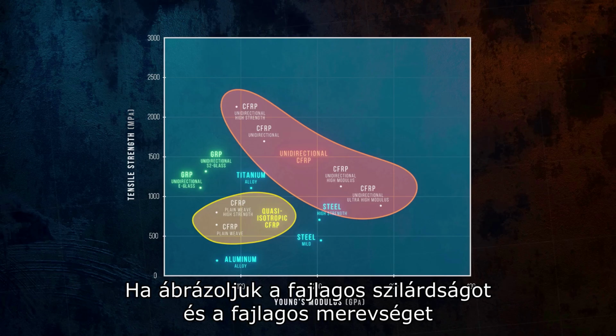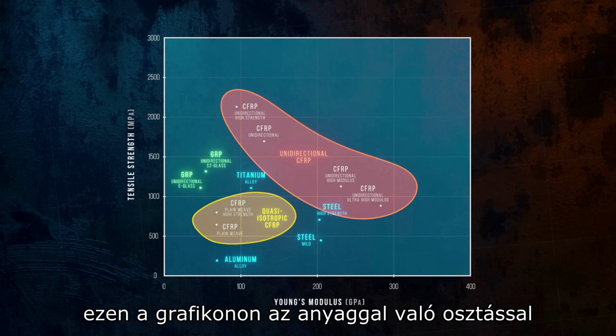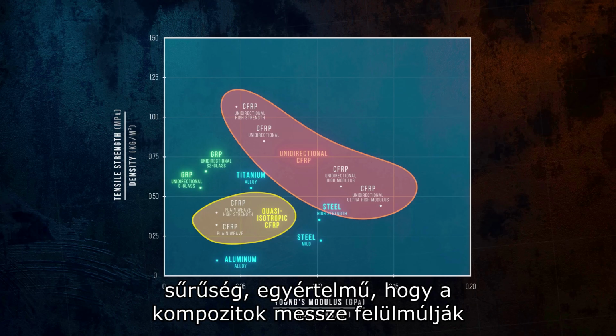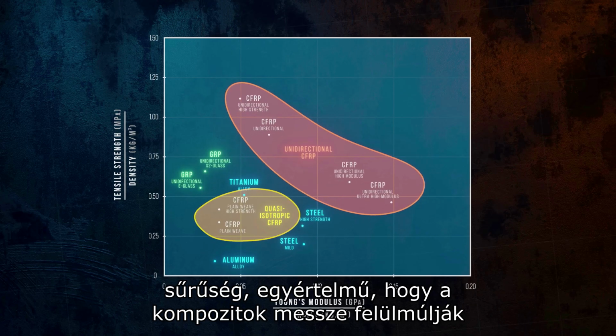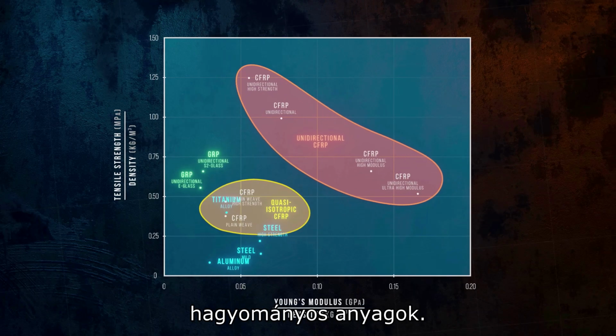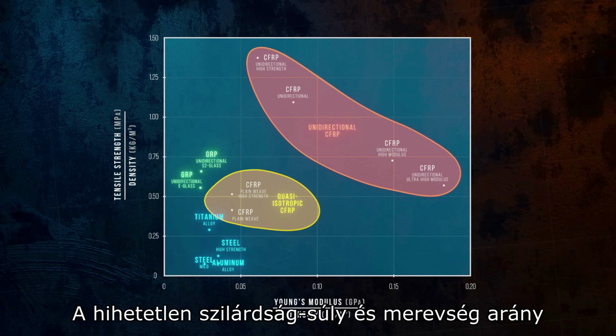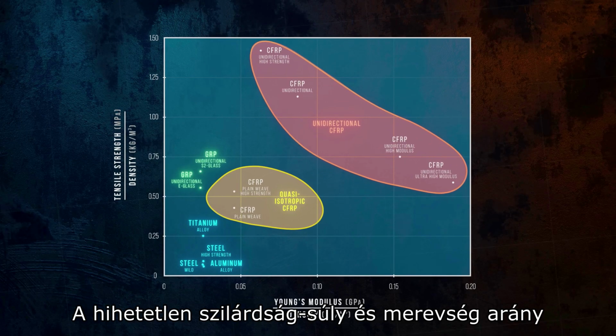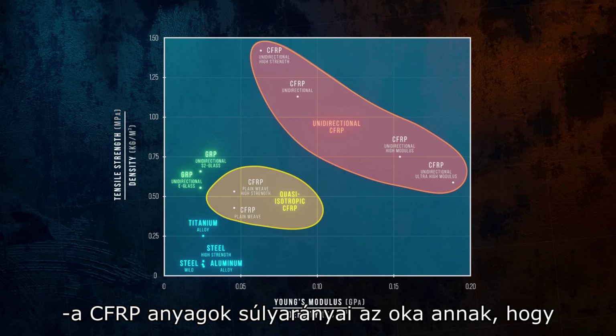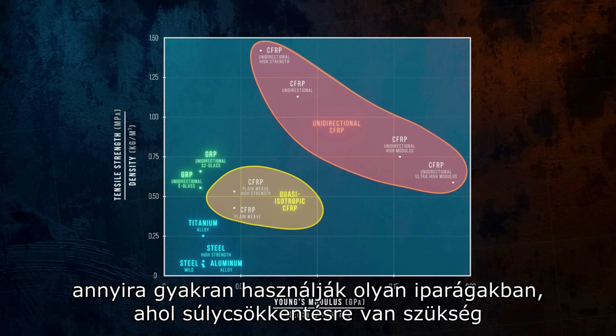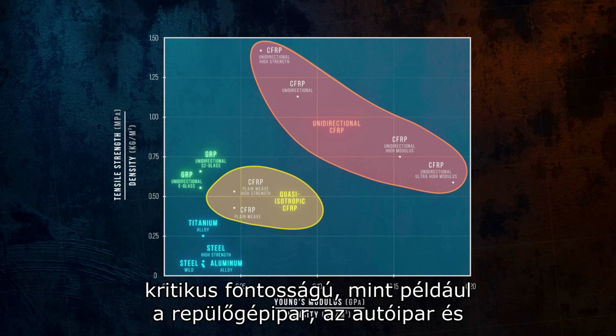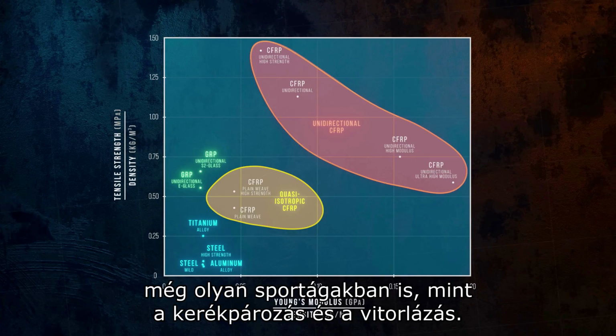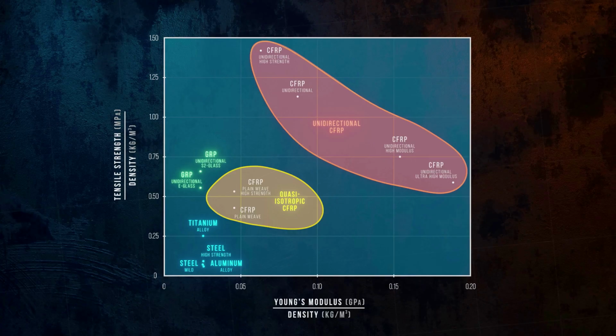The really amazing thing about these fiber-reinforced composites only becomes apparent when considering their mass. If we plot specific strength and specific stiffness on this graph by dividing by the material density, it's clear that the composites far outperform traditional materials. The unbelievable strength-to-weight and stiffness-to-weight ratios of CFRP materials are why they're so commonly used in industries where weight reduction is critical, like aerospace, the automotive industry, and even in sports like cycling and sailing.